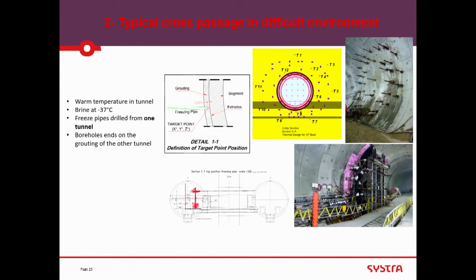And we drilled from one tunnel to the other and tried, this is very theoretical, to be as close as possible to the opposite tunnel. On the drawing, it's 7 centimeters, whatever. But what we had to do is control the temperature on this side. Instrumentation is very important in this project because, in fact, what we discovered is that we could not freeze this old area. The full area, the contact between the tunnel, where all the drilling arrived, could not be frozen.